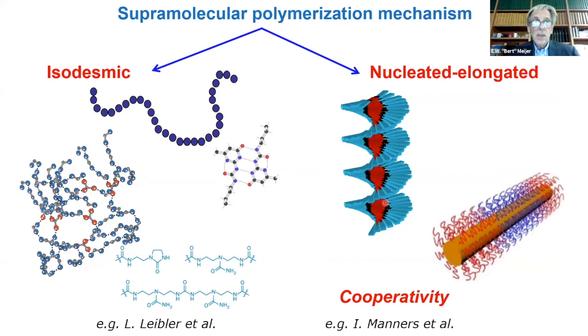And through the years, we came to the conclusion that there are many, many supramolecular polymers now. And if you want to characterize them, there are actually two types of mechanisms. One is the isodesmic, meaning that the association constant is independent of the chain length, and you have the nucleated elongated type of structures that starts with the nucleus and then grows. For people in polymer chemistry, you could say one is step, the other one is a chain type of polymerization. We were very happy to find out that the ordered structures are always nucleated elongators.